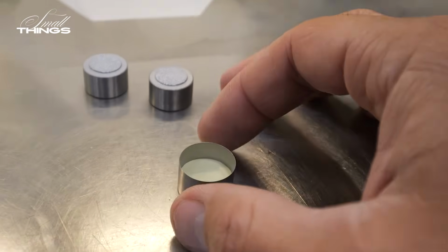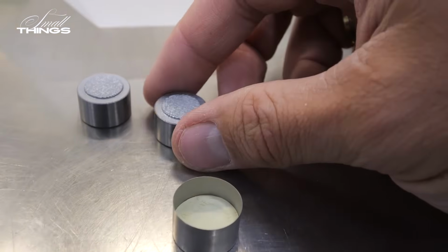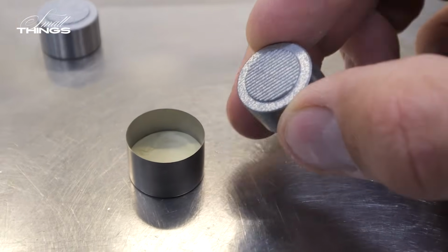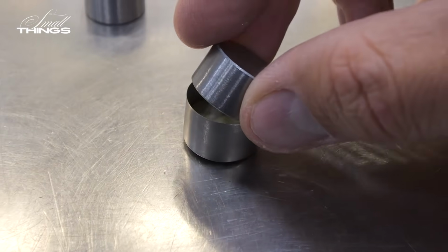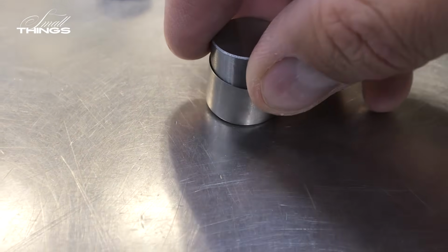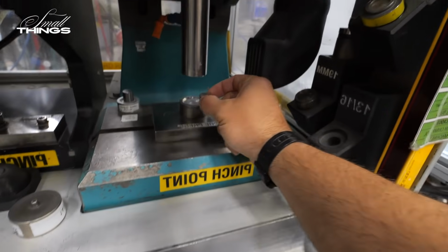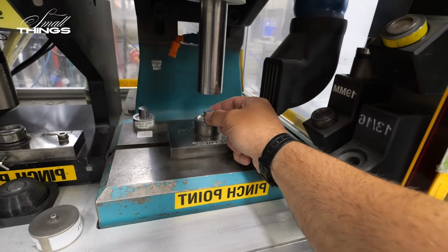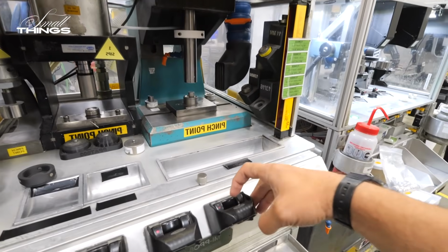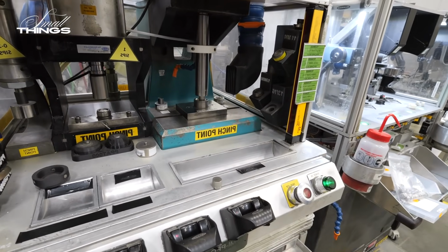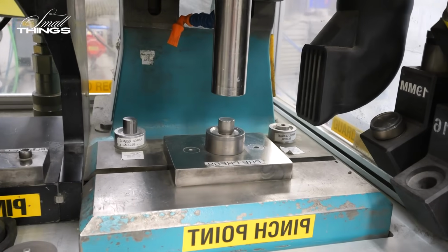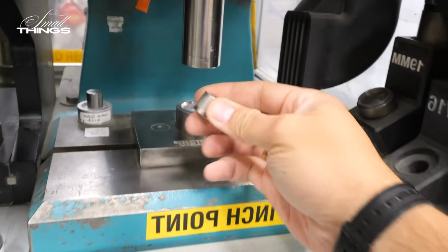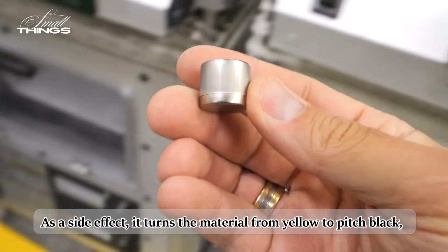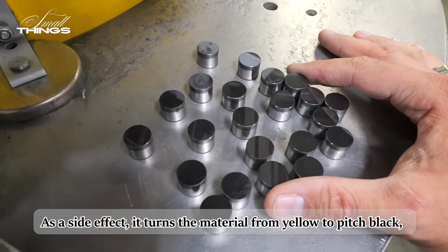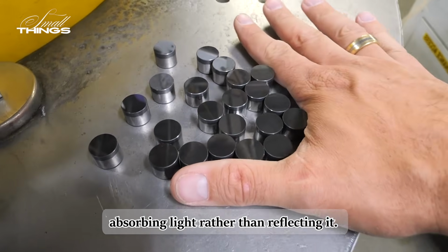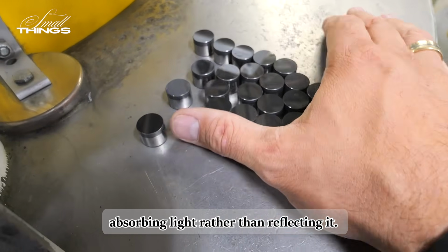A piece of cobalt-cemented tungsten carbide goes in alongside the powder as a base. Under the heat the press will generate, the cobalt liquefies and migrates into the diamond powder, acting as a catalyst that helps the individual grains fuse and crystallize into one unified mass. As a side effect, it turns the material from yellow to pitch black, absorbing light rather than reflecting it.